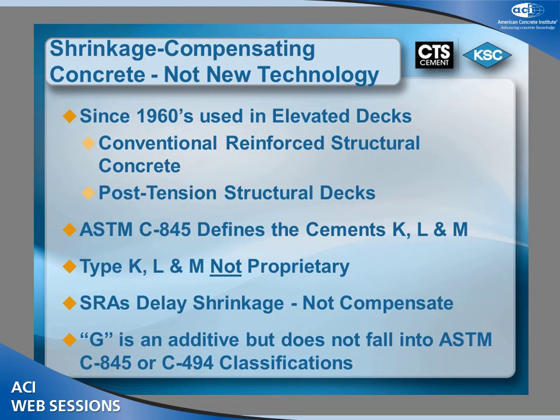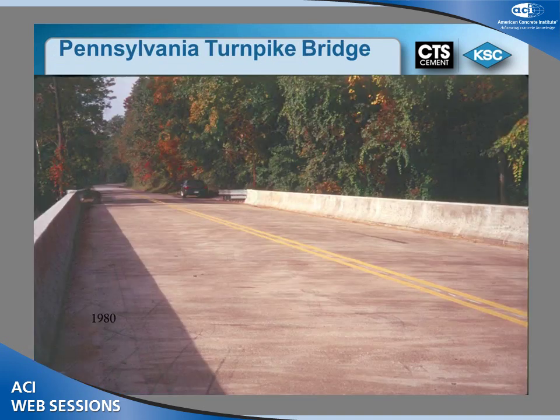So since the 1960s, with the use of concrete in elevated decks, conventional reinforced concrete and post-tension structural decks, we've started seeing the use of shrinkage compensating concrete get used more and more. ASTM C845 defines cements in the groups of K, L, and M. And interestingly enough, none of these are really proprietary at this point in time. We also know that the SRAs that are out there, the admixtures, really basically delay shrinkage. And the G additive, we're not really sure where it falls in. But interestingly enough, there's not much history in regards to the latter two that we're speaking of here.